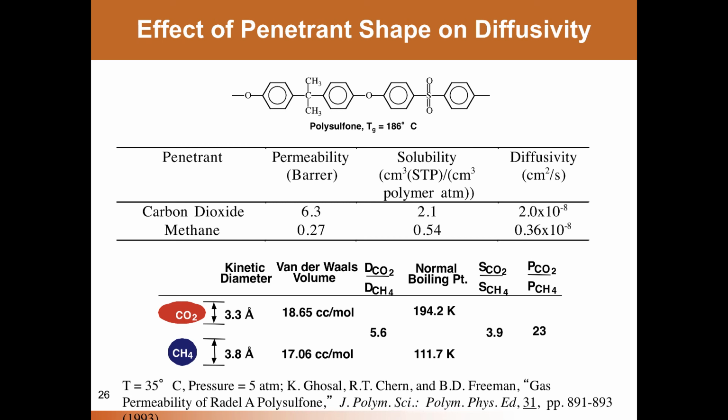And so if penetrant molecules are vibrating around inside free volume elements in polymers waiting for local scale molecular motion to randomly open a gap next to them so that they can take a diffusion step, the probability of having a small gap open next to a penetrant due to thermal motions of the polymer chain segments is much higher than that of having a large gap open up.